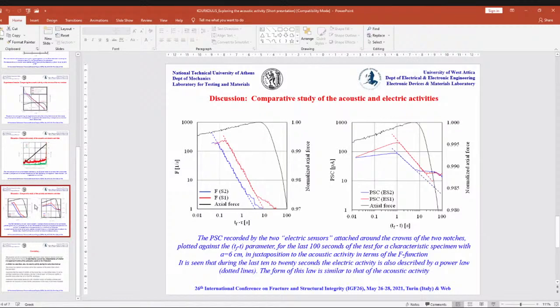This is our target, but it is very far from practical application because, as I mentioned, we have to check it for various materials. We have to take into account that most of the ancient monuments made of stone are cracked, so we have discontinuities, and it means that the signals will not be as clear as in a perfect specimen made for laboratory purposes. But already we have some structural tests with copies of the epistyles from the Parthenon, which are connected by metallic titanium connectors. Although there we have a much more complex system, it seems that both the function describing acoustic activity and the electric activity could provide, I emphasize, could provide. It must be checked, of course, for additional materials and additional loading schemes. It is promising, but not definite.